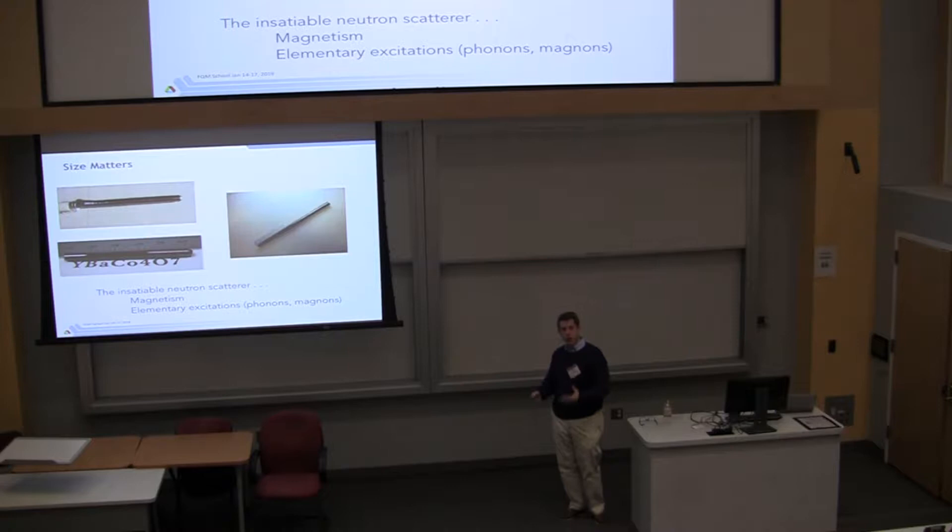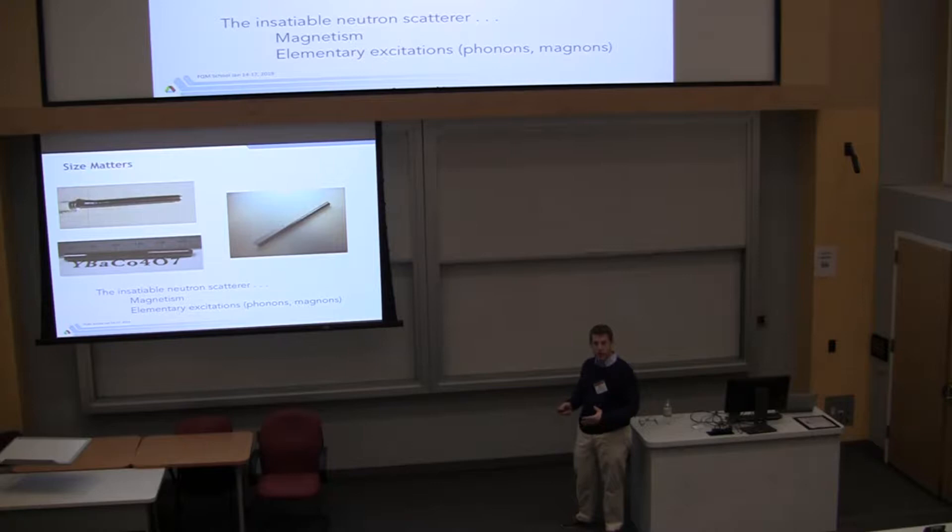Here's some work out of my own group from not quite a decade ago, looking at short-range order in these frustrated magnets. This is a different kind of frustrated magnet we created. And we used these crystals to do diffuse neutron scattering and extract from these patterns, sort of these underlying exchange constants that give rise to some unusual magnetic behavior that are engendered by these triangles and kagome layers that build together to make this material.